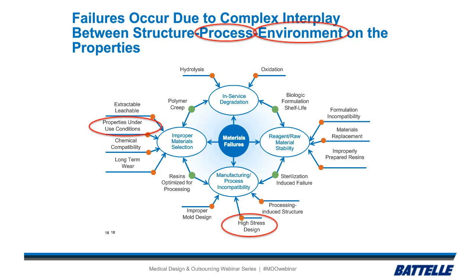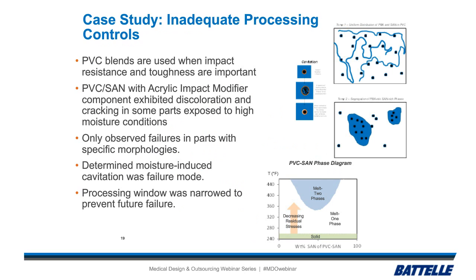The second example has to do with being able to mix components together. So this one, there was a PVC blend that was a styrene acrylonitrile and PVC with an acrylic impact modifier. This material, I guess the final device, what we saw was that some of them were discolored and became embrittled, and we were able to look at some good ones and some bad ones again. And what we saw when we dyed it and looked at the microstructure, we saw a difference in the domains. So the top right picture is a nice homogeneous mix of the components in this polymer system, and it shows that it makes a good, strong polymer.